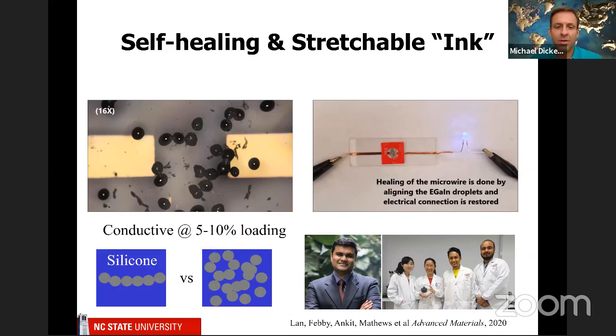Oh, here's my cartoon. I'm sorry that didn't appear. So again, what I'm trying to emphasize here is that this is a typical composite material where you have to put in high loading, and you need high enough loading to get these particles to percolate. But in our case, we can do low loading, and so you can actually assemble the particles. And one of the beauties here is that you can get inadvertent conductivity in regions where you don't necessarily want it, whereas here we can direct the particles to be exactly where we want them.